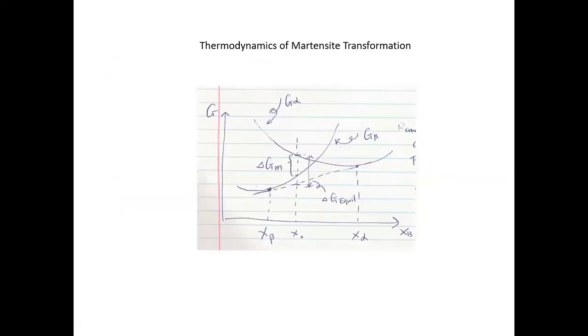Now, what is the driving force for the martensite? Okay, so let's look at this phase diagram. So now suppose I start with this X naught, right? And we know that we start with the alpha phase field, which is here. But now if I cool the system to, this is already the cooling. So in this case, at a particular temperature, you have these two free energy curves. And we know that if the system is in equilibrium, I should actually have the two phase coexistence. So the system is going to separate into this alpha and beta composition. Okay, and my free energy is going to be like here, right? So I can reduce the free energy by this whole amount, which is the free energy or the driving force for the equilibrium transformation, where I involve the nucleation and growth of the beta phase.